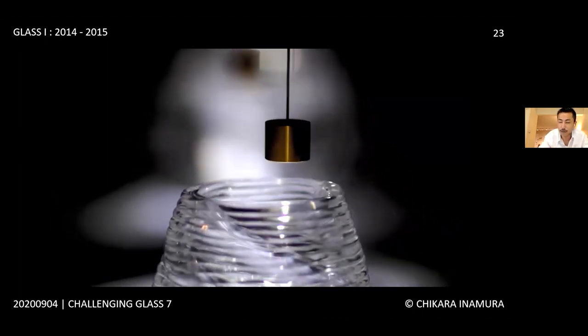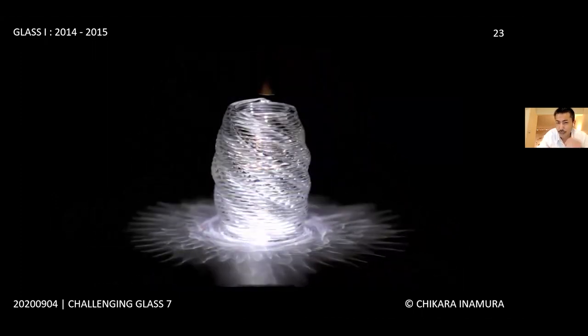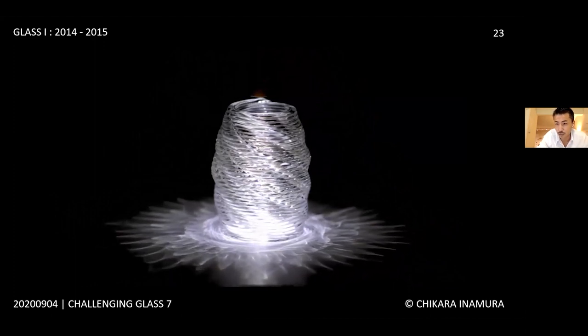We presented the collection of the first prototypes at the lobby of the Media Lab back in 2015. Printed glass objects have a beaded texture as a result of this extrusion process. This texture presents a unique opportunity for designing a dynamic illumination. Each layer of printed glass has a convex surface on both sides that acts as an optical lens and refocuses incoming light through refraction. By adding a single point light source above each printed glass, the products produce a highly intricate and dynamic illumination made of an overlay of caustics. Being able to control the lighting through the computational design is a clear advantage of 3D printing transparent glass.